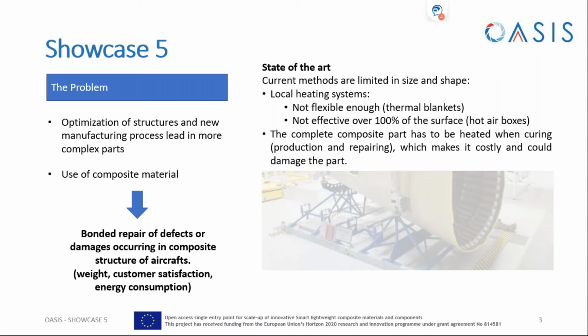So the state of the art allows us to repair this part. And we have two main options. The first is local heating, and the second is to heat up the complete part of the aircraft. In the case of local heating systems, in some cases they are not flexible enough to properly cure the composite material, for instance the thermal blanket, or in some cases this type of heating cannot be used on 100% of the surface of our structure, for instance the hot air boxes.